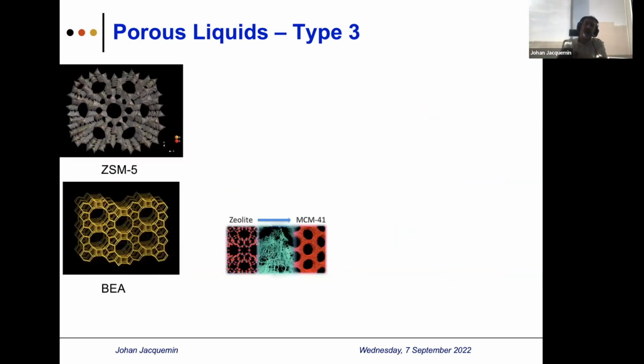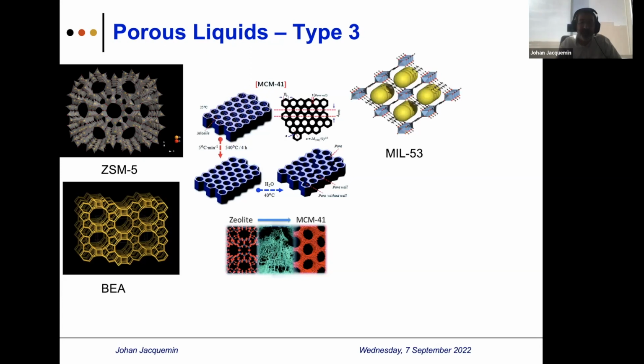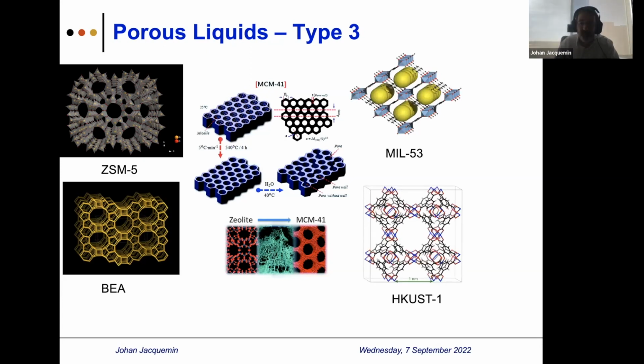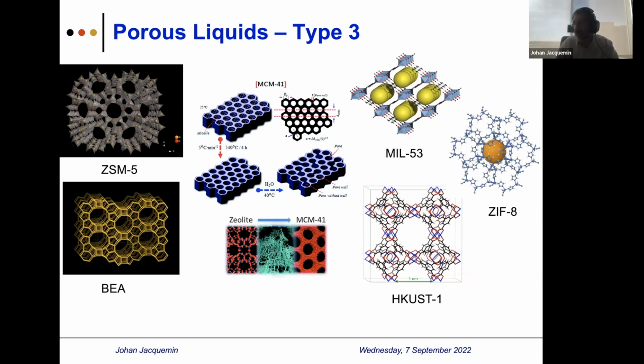Of course, type 3 porous liquids are a class of material which may be simple to form in the lab, because we can use any material from zeolite, move to MCM group, then to MIL, then to HKUST-1, for example, type of structure, and to ZIF, zeolite imidazolate framework, sorry. This is very well classified, I would say, mesoporous material, and the solid state isotherms are very well described in literature, and also very simple to measure by any BET technique, I would say, until you calibrate, of course, your equipment properly.